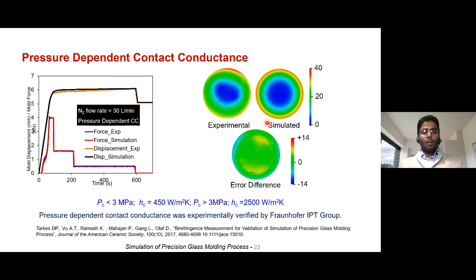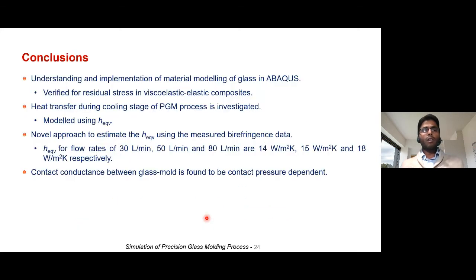So these curve fitted values were verified with the experiments. And the major conclusion we came to understand is that the heat transfer during the cooling stage is basically by heat conduction, and then there is a flow field which excavates this heat out. This was modeled by using an equivalent heat transfer coefficient, and for different flow rates we obtained the values shown over here.